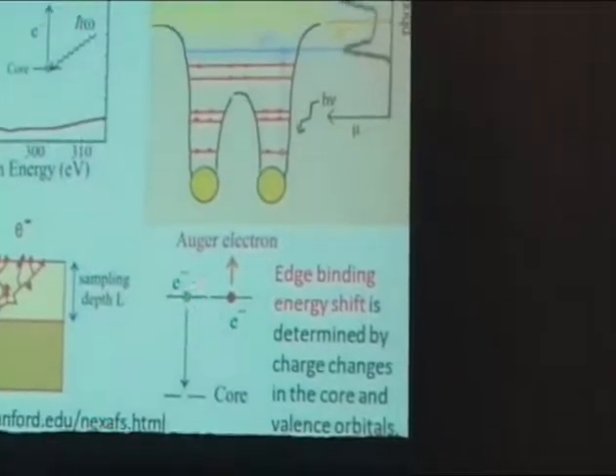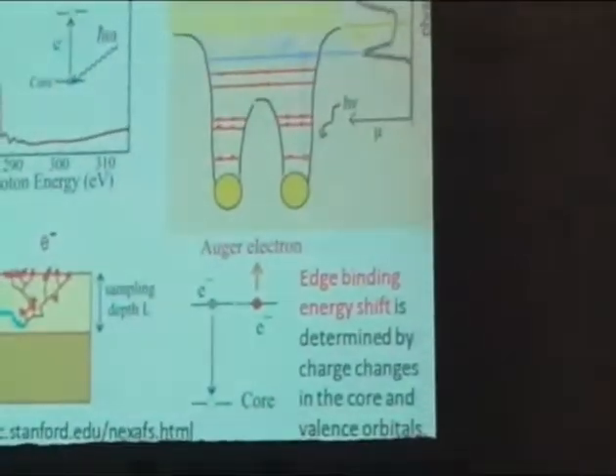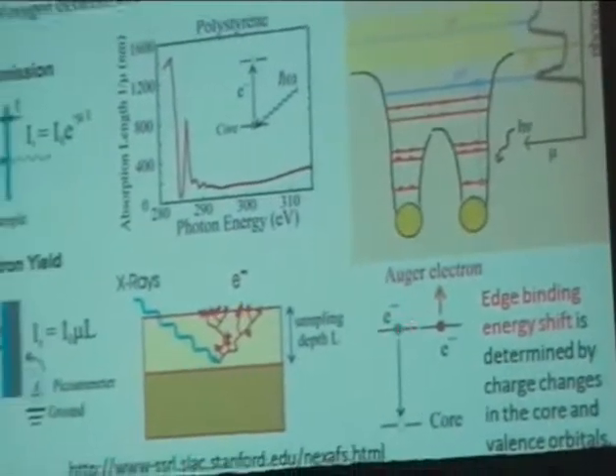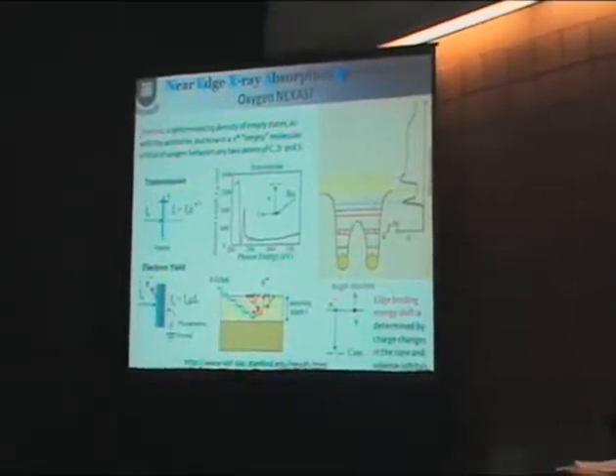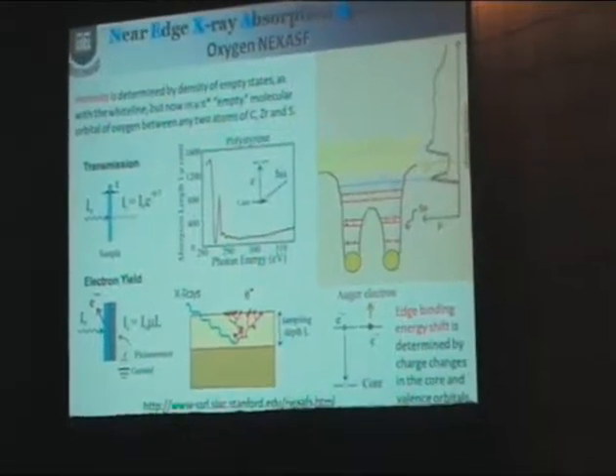other atom. And once excited, it can decay either by fluorescence or by Auger process, but light elements almost exclusively de-excite by an Auger process. And we're going to detect the electrons. That makes it quite surface sensitive, within 2 or 3 nanometers of the surface. But I want to make 2 statements about it.